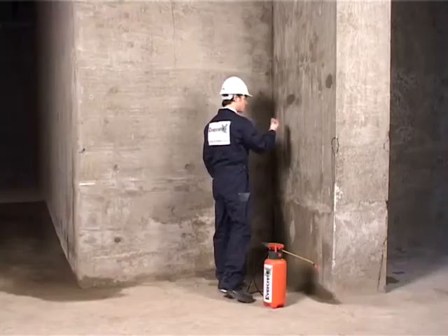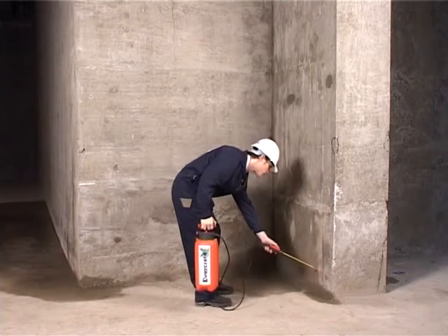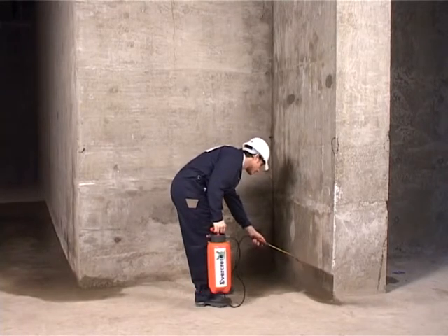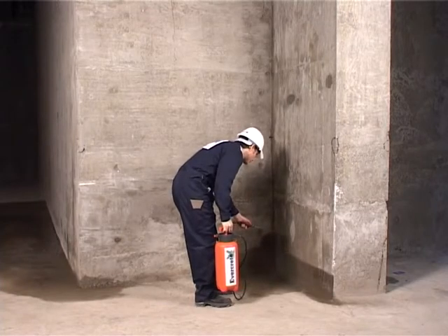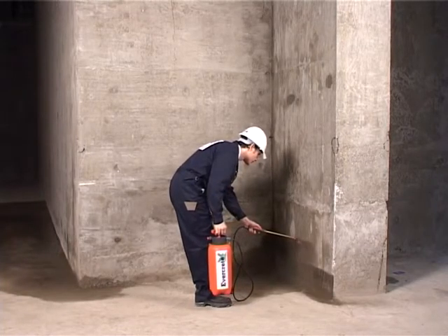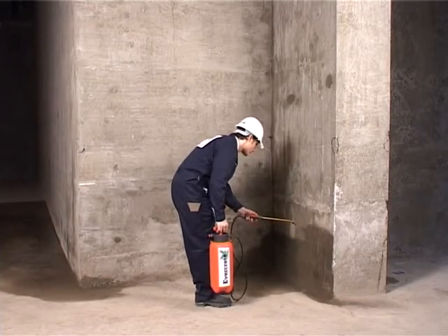Pre-wet your concrete surface first. When the wall is damp dry, slowly spray the wall starting from the bottom. This is very important so that any runoff goes into an area that has already been treated. A properly covered wall will be fully wetted with DPS and show reflections.